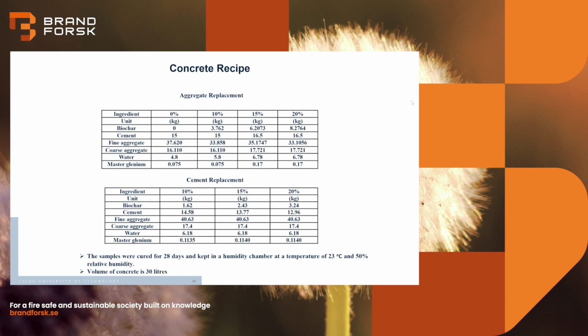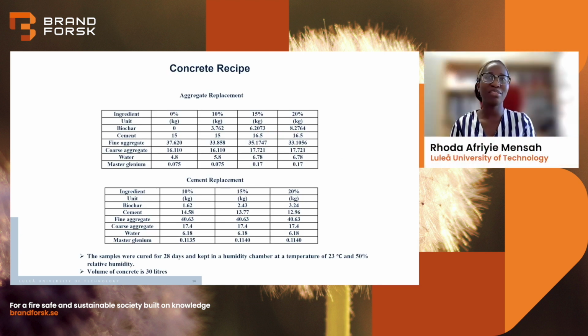Yes, sure. Thank you. So the recipe for the concrete we prepared for this project is shown on this slide. Two different types of concrete were prepared. The first one is the aggregate replacement concrete, where 10, 15, and 20% of the fine aggregates, which were between the sizes of 0 and 8 millimeters, were replaced with biochar, which had an average size of 2.95 millimeters. And for the cement replacement, 10, 15, and 20% of the cement were replaced with fine biochar, which had a particle size of between 100 and 400 micrometers.